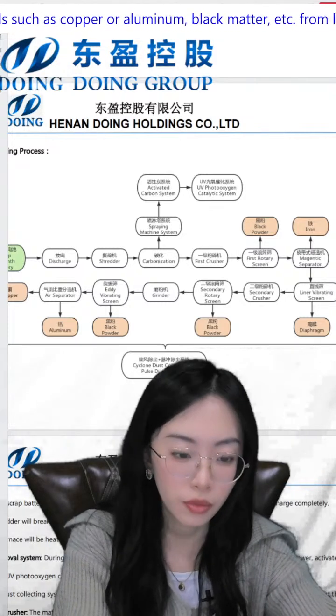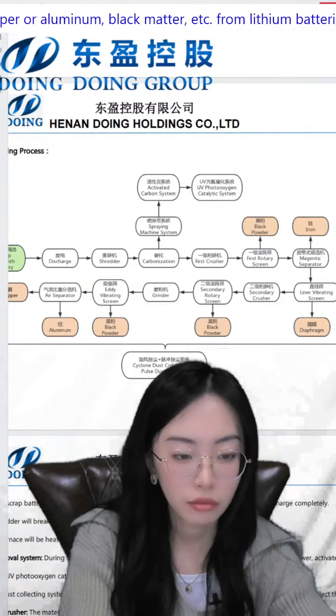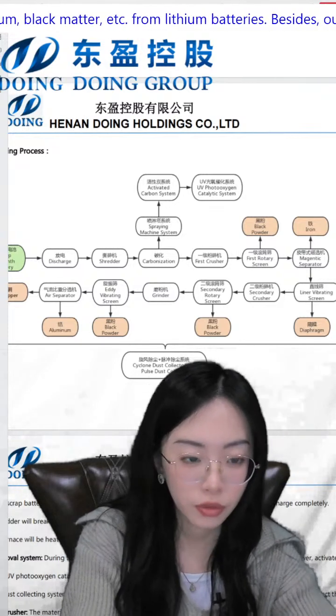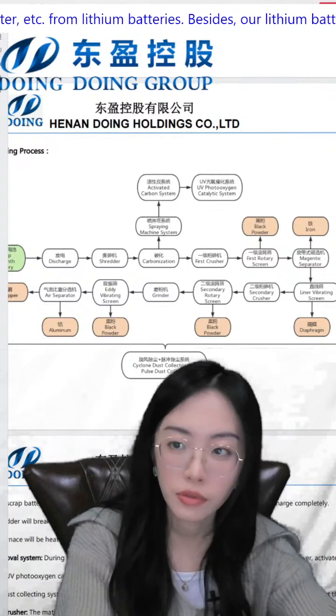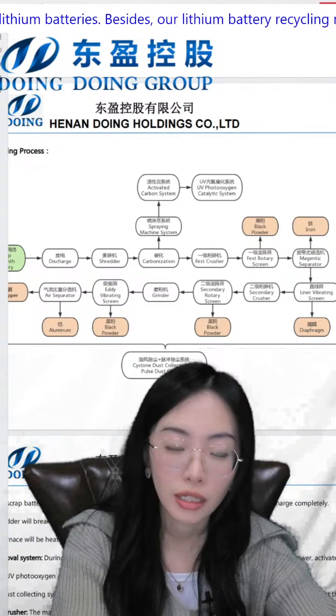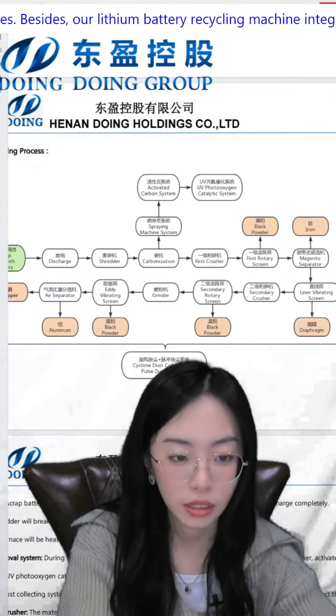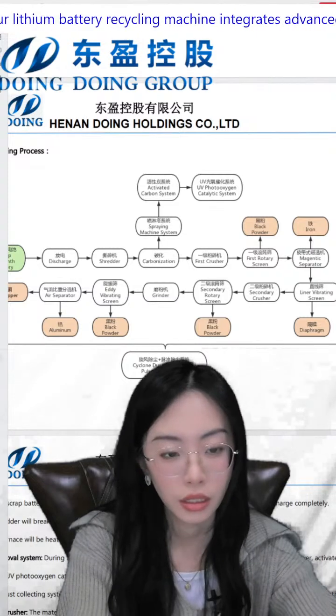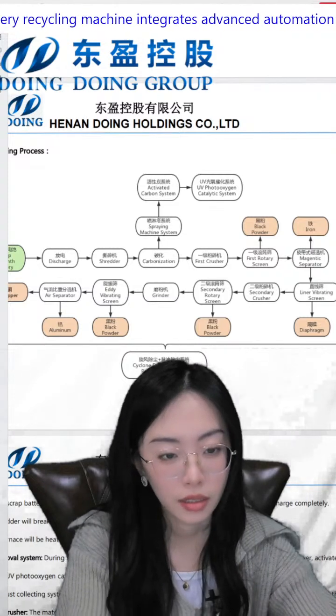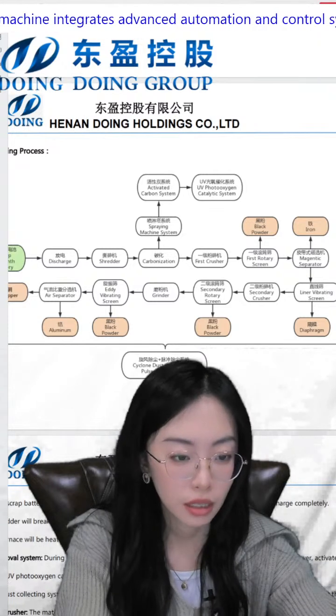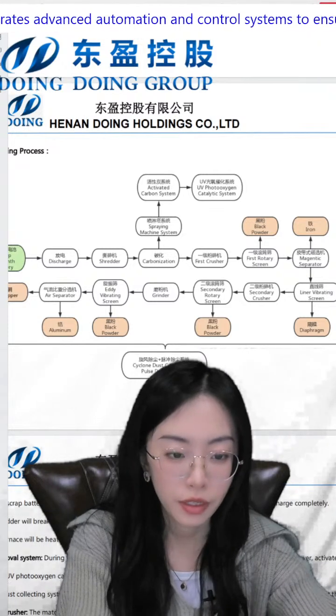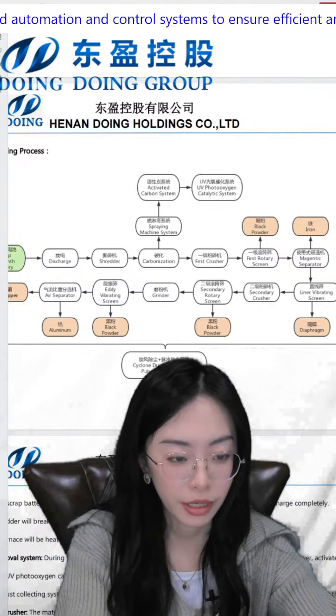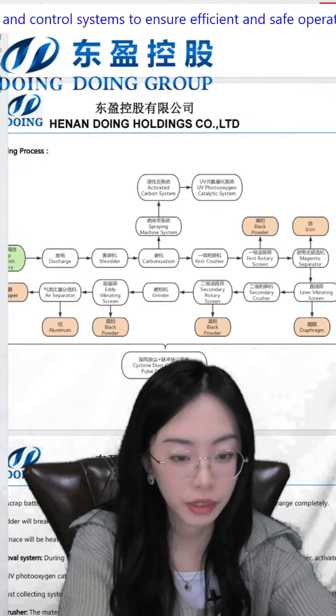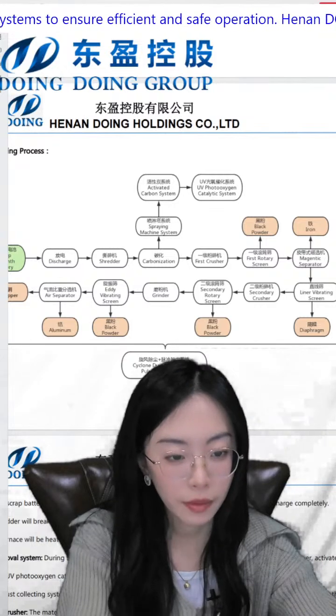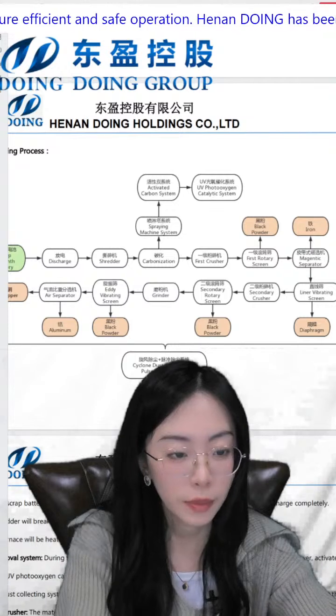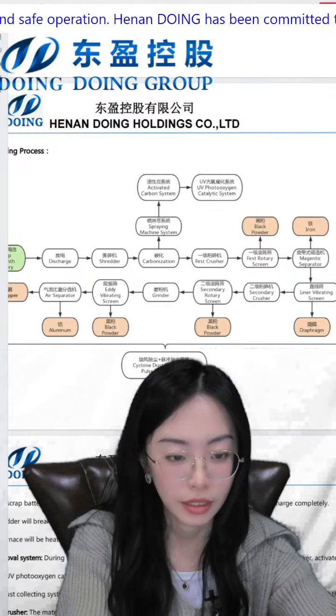And then this material will come to the rotary screen. It will do the first separation. This conveyor is not a belt conveyor. It's a sealed environment to prevent dust and other pollution. So we will use this sealed rotary screen, the first rotary screen. It will do the first separation to separate some of the black powder. In this step, after separation, about 60% of the black powder will be separated. This is the first separation.